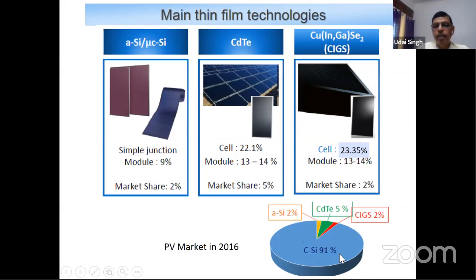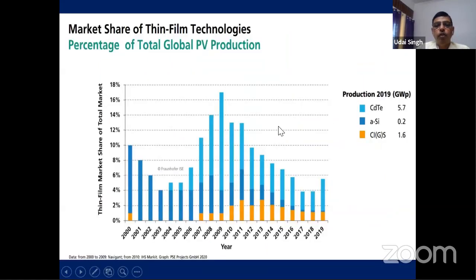Crystalline silicon you can see 91%, so not much has changed. Amorphous silicon may have reduced from 2% to less than 1%. Cadmium telluride has gained slightly, between 5 to 6%, and CIGS is still 2%. So there's not much change in the market share of these solar cells. If you see the production, this is your CIGS, which is less than 2%, and this small one is your amorphous, which is going dead. Maybe in 1 or 2 years there will be no amorphous silicon module.